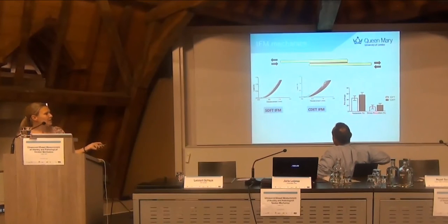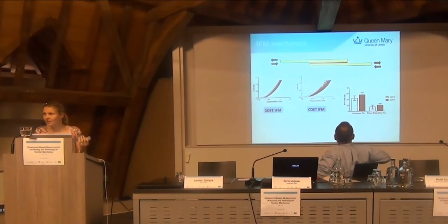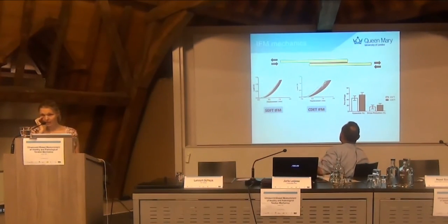We can look at hysteresis, stress relaxation. It's a reasonably high level of hysteresis, but it's not actually that much more than for a fascicle. It's 30% when we do this in a fascicle. This material is amazingly good at being able to cope, and we see much more elastic behaviour, less hysteresis, more ability to cope with cyclic loading again in the energy storing tendon, its IFM.